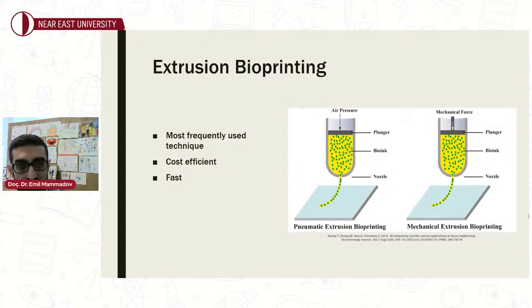Now we come to the most frequently used technique, which is extrusion bioprinting. Extrusion bioprinting is a method where we change our 3D printer nozzles to syringe barrels. We put our bioinks, with or without cells, inside those barrels, and we apply either mechanical force, air pressure, screw-driven force, or microvalves to push that bioink onto the build plates. Generally, we use Petri dishes as the build plates here. So this is the most cost-efficient and the fastest way to make three-dimensional constructs.